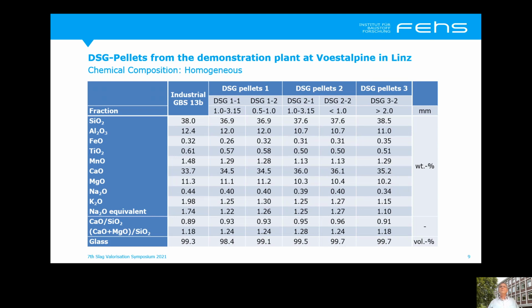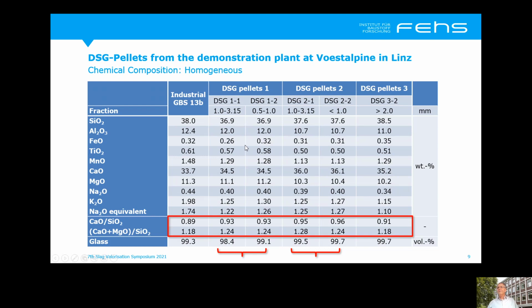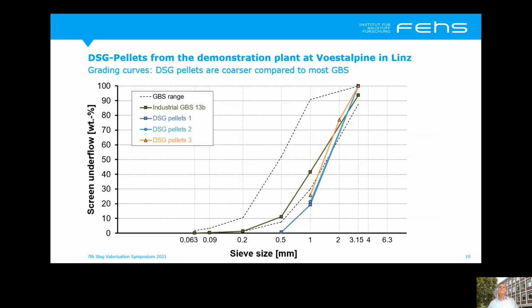The chemical composition of as well the industrial GBS 13B, which was our reference, as all DSG pellets from the 3 campaigns was very similar. In particular, the chemical composition of the different fractions which we separated from the pellets from the same campaign were very similar. All in all, the slags had a low basicity, so the reactivity of all slags was in general lower compared to other slags which we have in Europe.